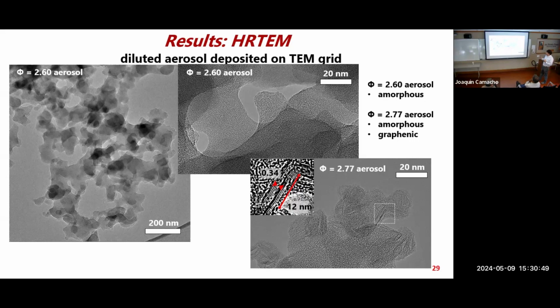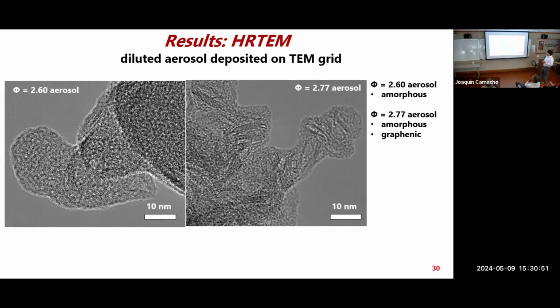And then if you go across the areas, you'll see different examples where there are some amorphous structures, but there are definitely these distinct, this is not soot, this is graphene ribbons here. And it's not a complete, clean, uniform structure of graphene ribbon, but it's clear that it's there, and it makes sense of where this Raman spectra came from. There's probably these crystalline graphene sheets that give the Raman response that I've seen earlier.